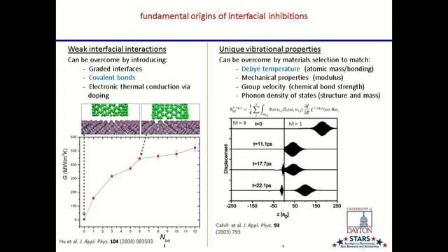Waves propagate much differently through a carbon nanotube, with its very stiff bonds, than they do in a more ordinary, floppier material. And that causes some problems. You can see how that's manifested in this simple simulation where there's a heat pulse propagating through this solid that has one set of vibrational properties. This material has 4 orders of magnitude different vibrational properties.